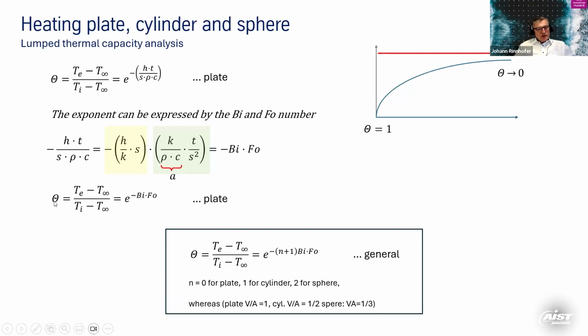The dimensionless temperature difference is e to the power of minus Biot times Fourier. And that can also be generalized. You can calculate the end temperature from this expression, which has an n plus 1 factor. n is 0 for the plate, 1 for the cylinder, and 2 for the sphere, because you have different volume to heated area relationships. As I said, we don't go into too much more detail. So that's all good for thin stock, lumped thermal capacity analysis, Biot number less than 0.1.